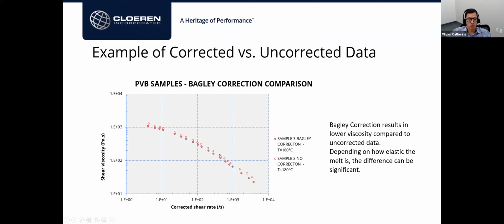You can see here again another example. Depending on the melt elasticity of the polymer, this may or may not be as big as this one. In this case, I would say it's a moderate correction. I have seen melts that were much more elastic where the uncorrected value was much, much higher than the corrected value. Again, keep in mind that because you're removing an entrance pressure, your corrected pressure will result in a slightly lower viscosity compared to uncorrected.